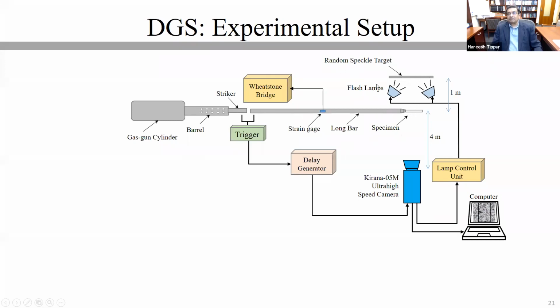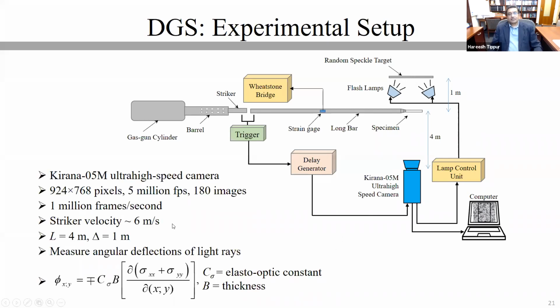The setup basically consists of a planar surface which is placed behind. This is the top view of the setup. So there is a planar surface that is kept behind the specimen, and this specimen has random speckles sprayed on it. And we are photographing these speckles by a high-speed camera, which is running at 1 million frames per second. The details of the camera are exactly same as before. And what we are measuring by this experimental setup is the angular deflections of light rays.